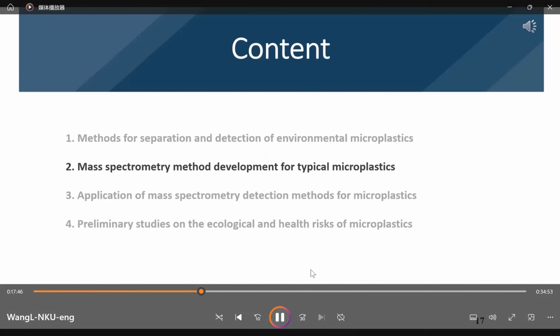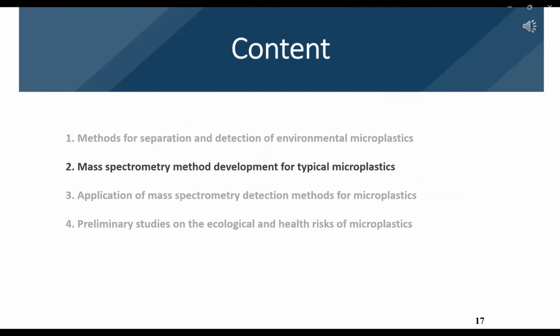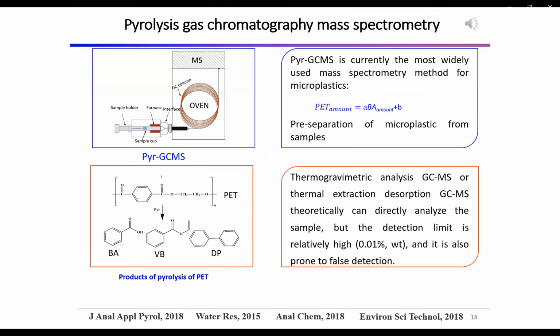Due to environmental aging, it is difficult for us to achieve an ideal recovery rate for environmental microplastics. Therefore, we attempt to change the detection method to avoid sample pretreatment. We consider mass spectrometry detection technology. Mass spectrometry detection technology, such as pyrolysis gas chromatography, has been commonly used in microplastic detection. This method pyrolyzes polymers into small molecular fragments and calculates the concentration of microplastic polymers through the concentration of the fragments. However, due to the lack of selectivity in fragments, this method still needs to separate the microplastic in advance.